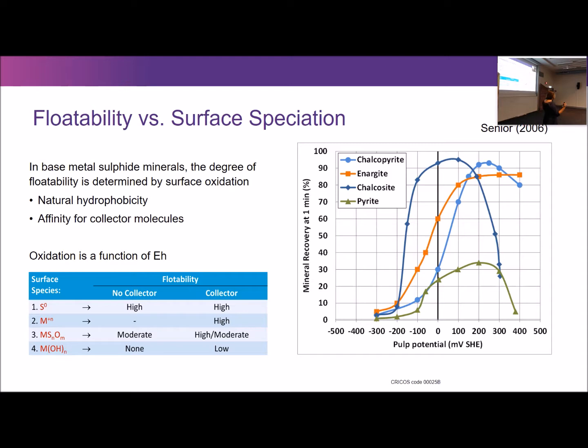When oxidation initially kicks in, the first thing that happens is you have elemental sulfur being deposited on the mineral surfaces. Elemental sulfur is completely water insoluble, so it forms this beautiful, completely hydrophobic layer on the mineral surfaces. Things float like crazy in the absence of collector, but sulfur also reacts well with collector, which further boosts the floatability. So this corresponds to this lovely peak right here.